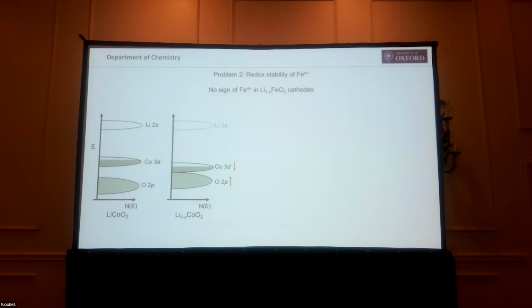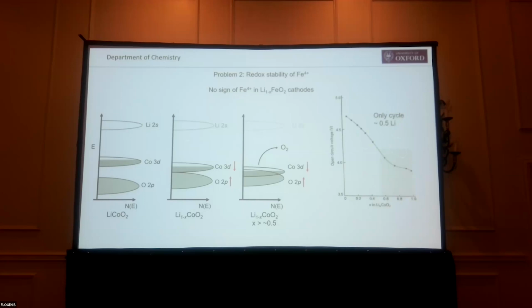So actually the oxygen band is coming up while the cobalt band is coming down. And you get to a position now where the top of the valence band is actually the oxygen, not the cobalt. So in LiCoO2, we haven't used half of the capacity, because if we go any further, we start oxidizing the oxygen. And the problem for iron is exactly this. How do we stabilize iron 4+, because we really don't see any sign of it. So this is problem number two. How do we stabilize iron 4+, or how do we stop the anion redox ruining the valence?